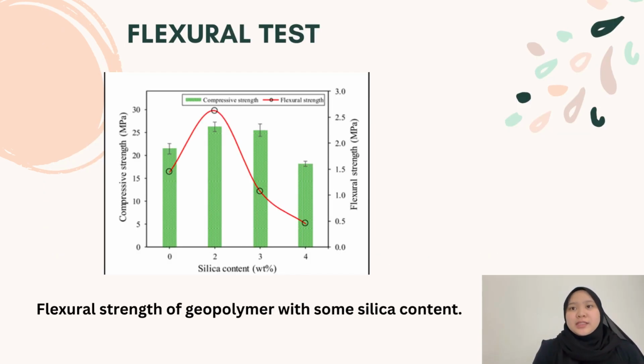This is for the flexural test. The result indicates that the flexural strength follows the same trend as the compressive trend, and it was confirmed by other studies that the addition of nanoparticles increased the strength of geopolymer cement paste. The addition of nanosilica particles began to affect the flexural strength of the geopolymer.